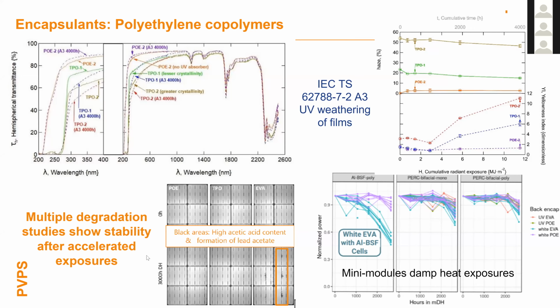The bottom row of figures shows little 6-cell mini modules exposed to 0 hours, with POE, TPO, and EVA, and then to 3,000 hours of damp heat. What you see in these bottom ones is that there's actually corrosion at the grid lines with EVA, but not with POE and TPO. This is because the EVA is hydrolyzing and causing corrosion of these grid lines, but we don't see that in TPO and POE. This suggests that they're not inducing that same degradation mechanism, since they don't have that acetate group.